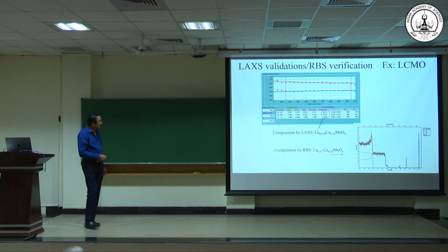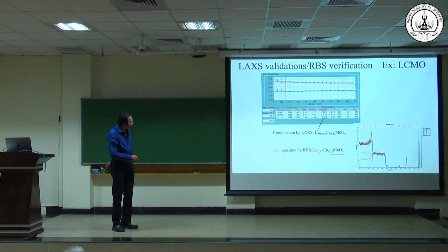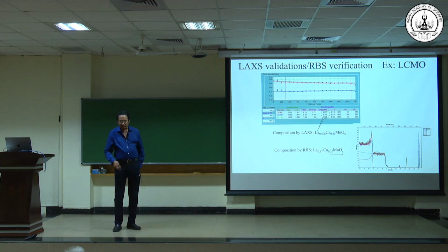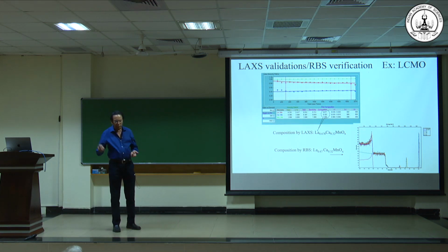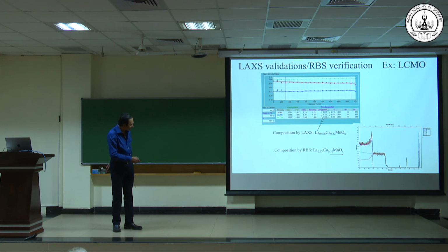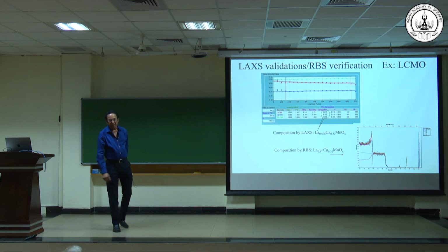So here, for example, is the composition of a complex film. Lanthanum 0.678, calcium 0.32, Mn. This is the composition measured instantaneously as the film is growing. Okay. Then we take the film, we send it to California to Charles Evans. They do Rutherford backscattering and they measure it. The film comes back to us 3 weeks later, right? And look at the composition of the same film. Okay. Lanthanum 0.67, calcium 0.32, MnO3, right? The difference is we got this number instantaneously as opposed to waiting for 3 weeks, right?